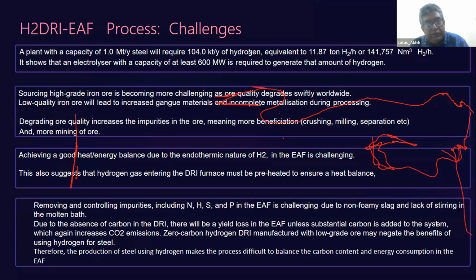The third one is, as in the last slide I had shown, that it is endothermic. So it needs heat, it needs energy. If it is endothermic, then it cannot produce as much iron as the BF and BOF produce. So achieving a good heat energy balance due to the endothermic nature of hydrogen in the DRI furnace is a challenge. This also suggests that hydrogen gas entering the furnace must be preheated to ensure a heat balance. It must be preheated.